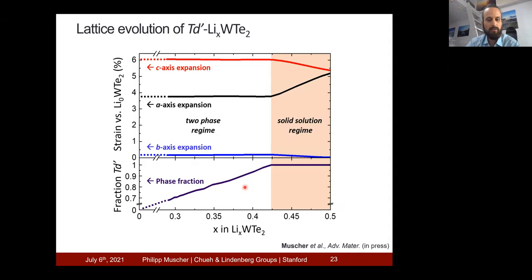So here I'm depicting by how much these parameters are larger in the TD prime phase compared to pristine tungsten ditelluride. You can see while we are in this two-phase regime, where one phase is growing at the expense of the other, the lattice parameters in the new phase are constant. However, once we have 100% of the TD prime phase, we can still insert more lithium.